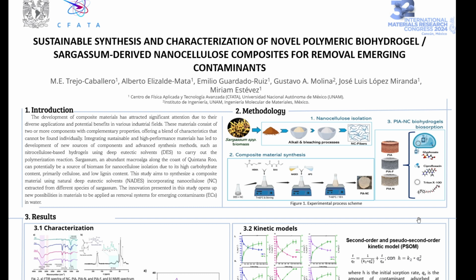Next, the two nanocellulose samples extracted from fluitans and natans species were dispersed in the deep eutectic solvents. The amount added was based on the maximum solubility of the solvent. Once the nanocellulose was dispersed and the mixture was homogeneous, the monomer hydroxyethyl methacrylate and the cross-linker bisacrylamide were added. After that, the natural deep eutectic solvent was poured into the mixture. Subsequently, an ammonium persulfate aqueous solution was incorporated to start the free radical polymerization.